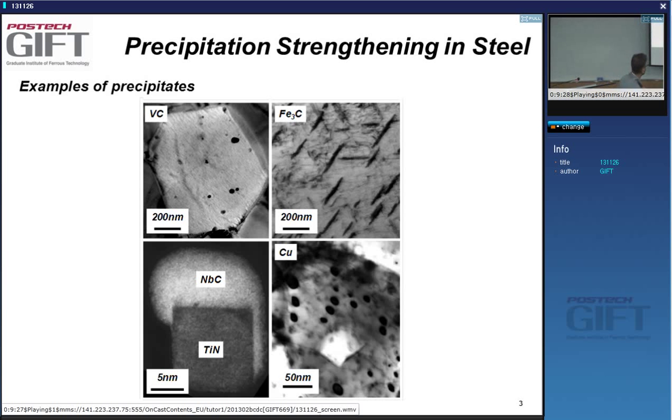And you can see here, this is a micrograph. You can see all these dots here are basically copper precipitates. Again, inside, you can see the grain here, grain boundaries here, yes. You can see it's inside the grain. And that's a necessary condition for precipitation hardening. So when you look at this, what can you see? Well, obviously, there are going to be very important parameters to precipitation strengthening.